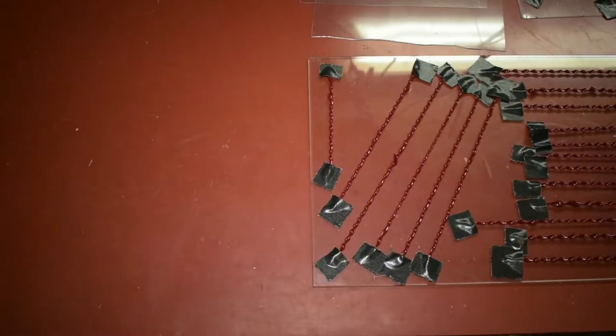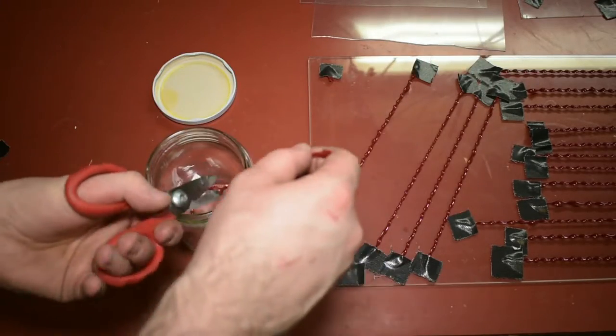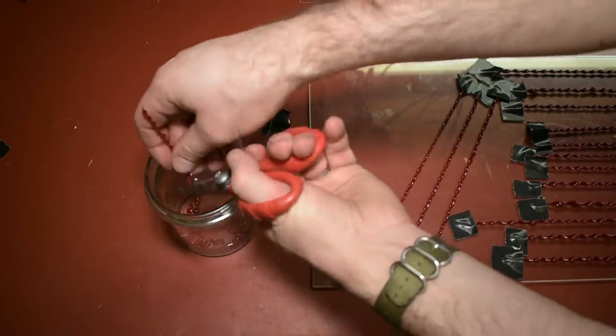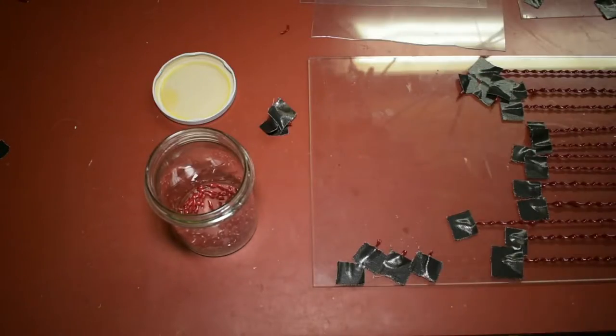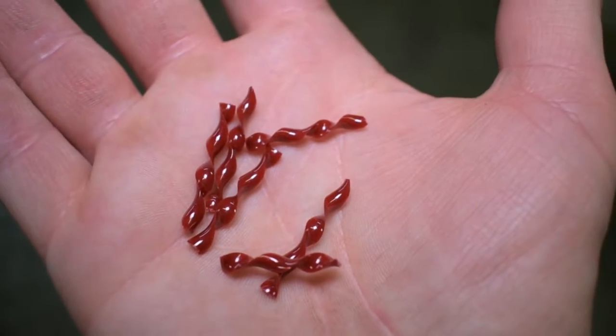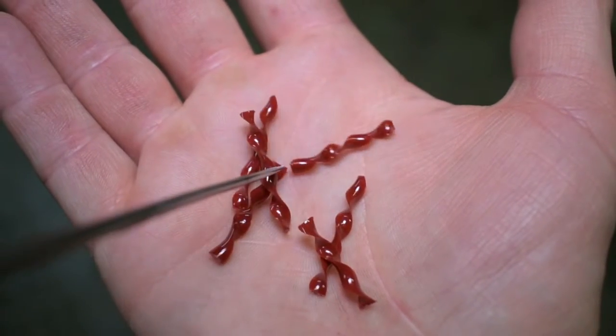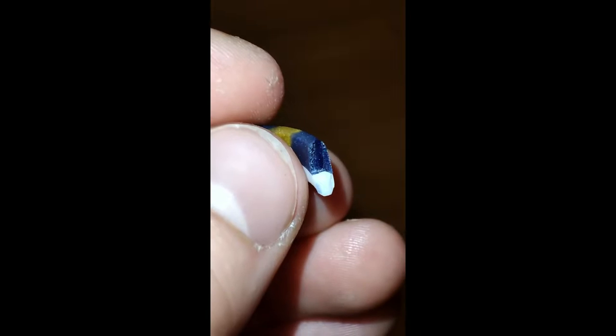The curlies have now all cured and I can take them off the acrylic sheet one final time to cut them into smaller pieces. Now I have all these little red curlies, which I could simply dump into the mold and pour the base colors on top. There is a problem, however — the surface is really smooth and when you're trying to bond something together, like it will be the case with the curls and the base colors later, you ideally want a rough surface finish, lest the two parts separate easily under stress. I've already tested this and the test ring, after dropping it down a flight of stairs multiple times, always broke exactly across the surfaces where the highlight parts meet the other resin.